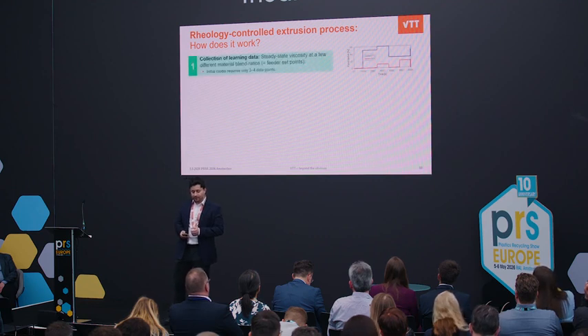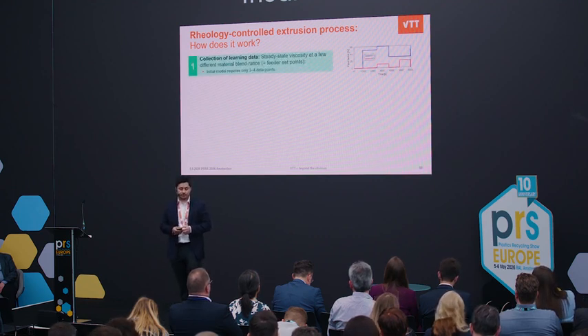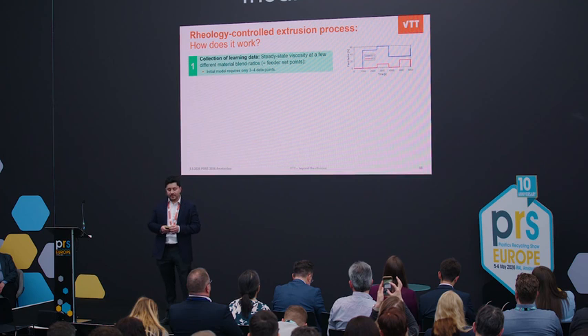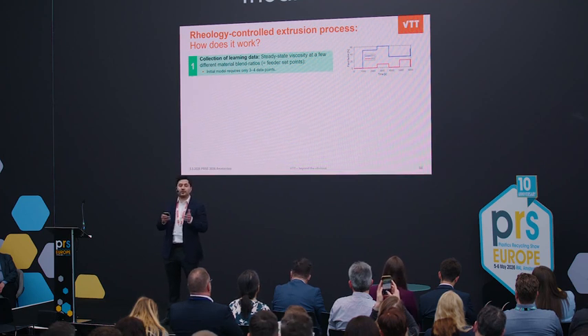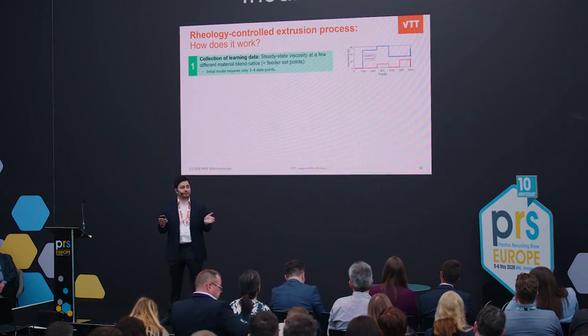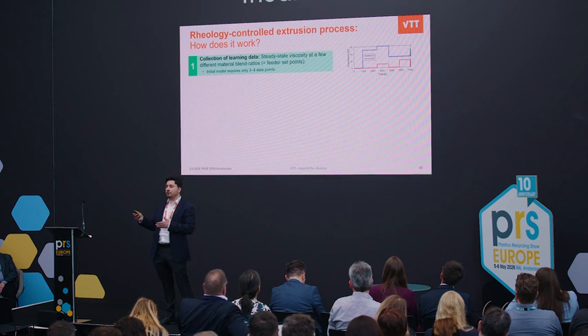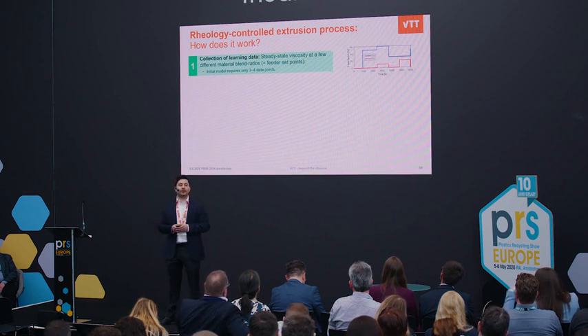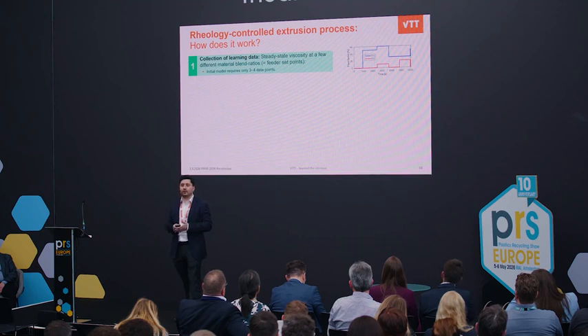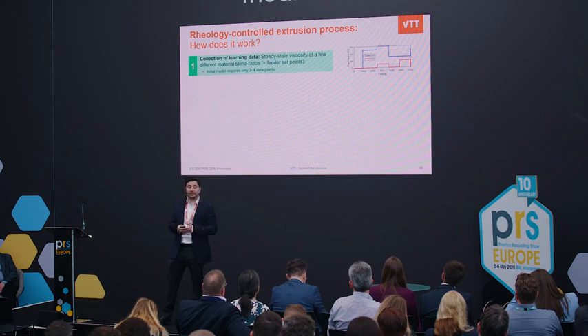So how does the rheology controlled extrusion process work? This is where we first collect the learning data. If you have a waste feedstock, the equipment will be run for as many hours as you would like, 6 hours, 24 hours, maybe only a few hours. And then you will get a few different material blend ratios.